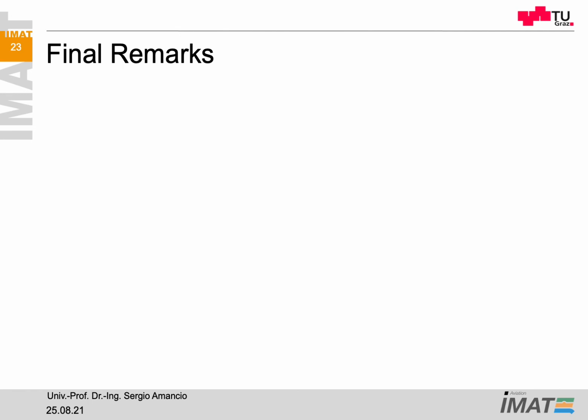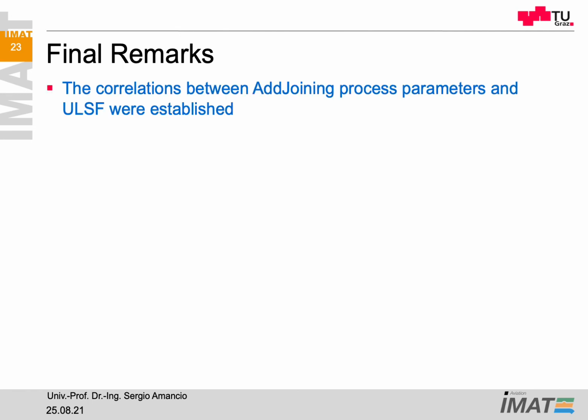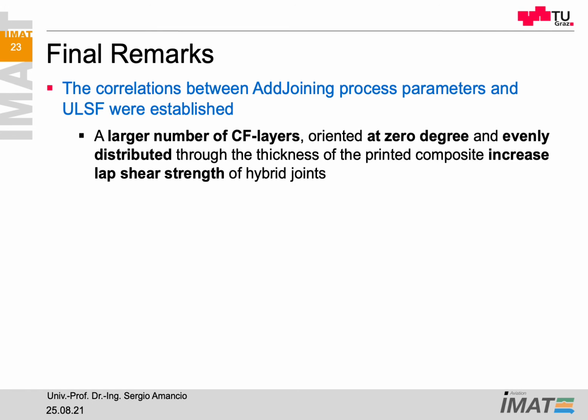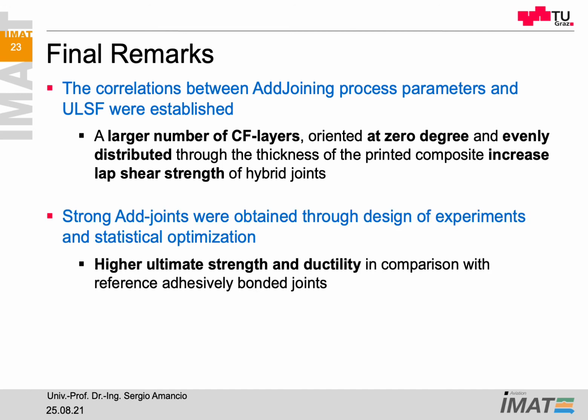So with that, I can finalize this presentation, summarizing first of all that the correlations between the AddJoining process parameters and the ultimate lap shear force were analyzed and established, whereby we saw that the number of layers, the orientation of the layers, as well as the types of distribution of those layers, will influence the lap shear mechanical resistance. And in comparison to the state-of-the-art adhesive bonding, we are able to produce stronger joints with better ductility, showing the potential of this technology.